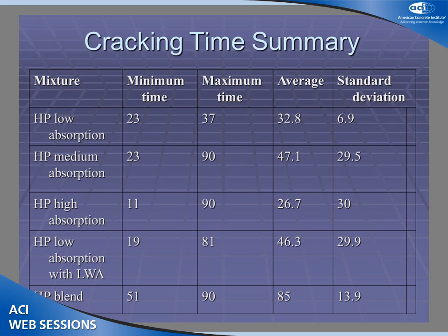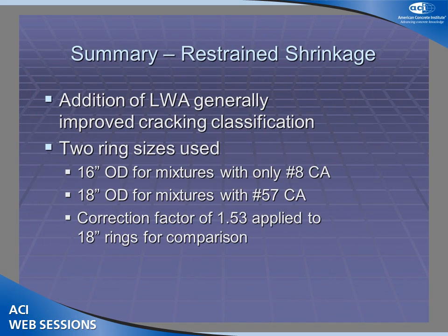But what we did find is that when you included the lightweight aggregate, you generally can bump up about a category. You generally improve your properties. So we decided that we thought that looking at the data across the board, adding the lightweight aggregate, regardless of your original cracking tendency, tended to make that concrete more resistant to cracking. The problem we had is we looked at 16 and 18-inch rings, and we used a correction factor for the 18-inch rings, and when you go to an 18-inch diameter ring, it is a relatively thick donut of concrete. It's quite frankly kind of hard to get it to crack.